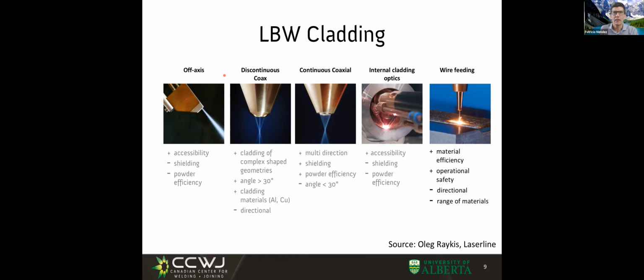So one way of feeding powders into the weld pool is what they call off-axis. So it comes from this side. The beam would be coming more or less here between the separation between the two figures. The weld pool would be at this level, and we melt this area with the beam, and we bring the powders on this side. What is good about this is it's easy to access.